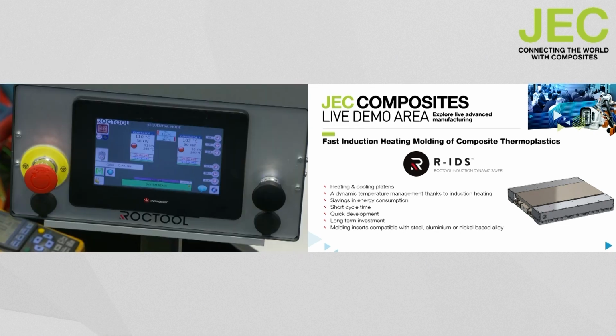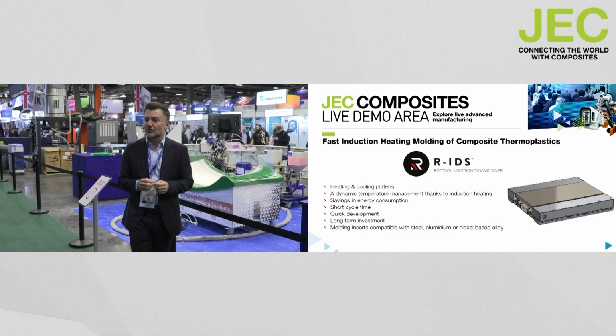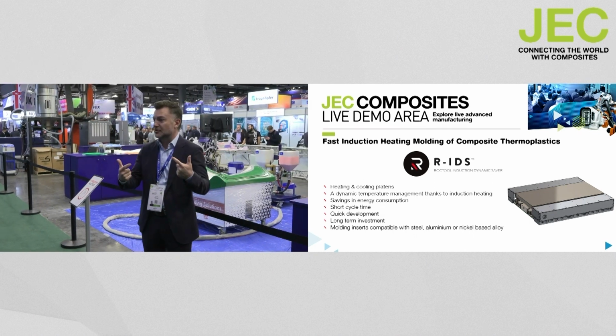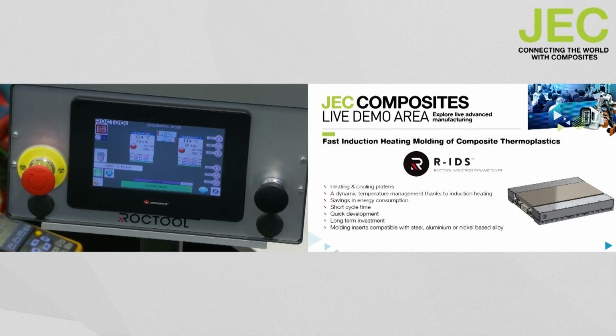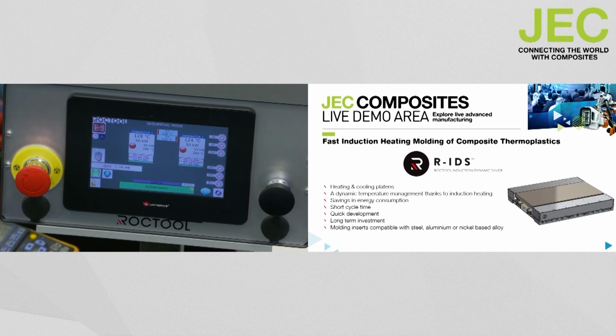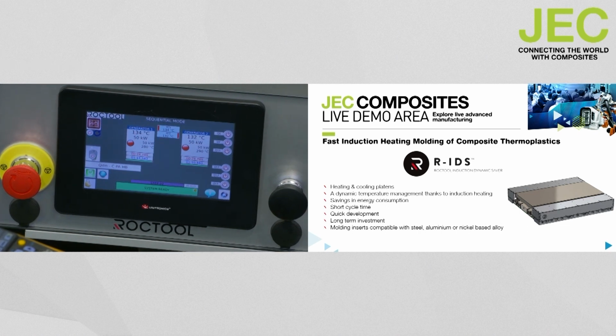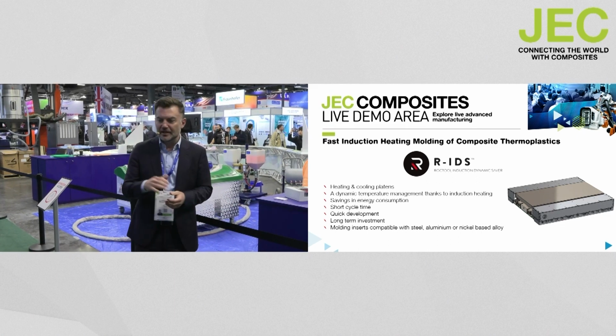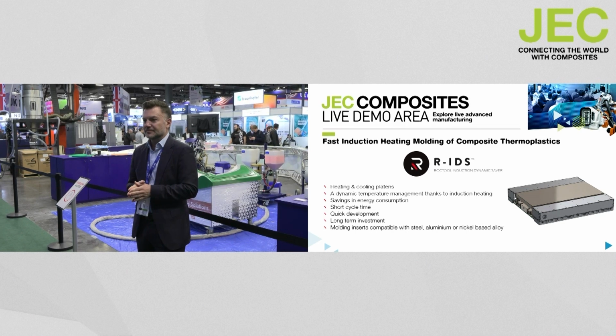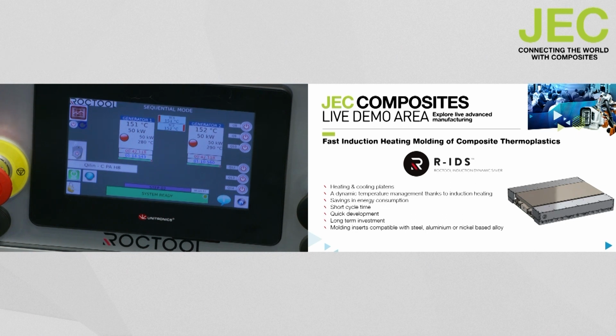So Hugo over there, who we did not introduce, is in charge of the demonstration on the molding side as a Roctool engineer. We have thermocouples located on the heat platen where we can monitor the temperature. We can also have thermocouples inside the mold inserts to know exactly what the temperature is on your mold surface, based on the temperature you need for your consolidation or for whatever you're trying to achieve with your material. So in that particular case, we need to heat up our platen to about 250 C. And then we will have a heat transfer to the insert to mold our material.